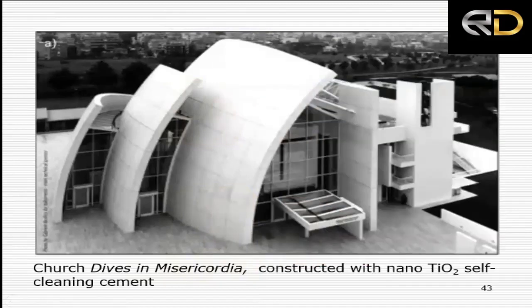There is a building in Rome which has used nano-dimension, 20 nanometer size, titanium dioxide in it and coated. And the building was constructed sometime around 2000. So far, within 25 years, there was no whitewashing or anything, and the building is as clean as new, because this nano titanium dioxide acts as a cleaning agent. And most of the dirt comes because of the organic contaminants. And in the presence of ultraviolet light coming from the sun, this acts as a cleaning agent and decomposes them and